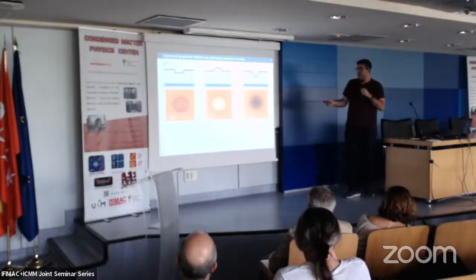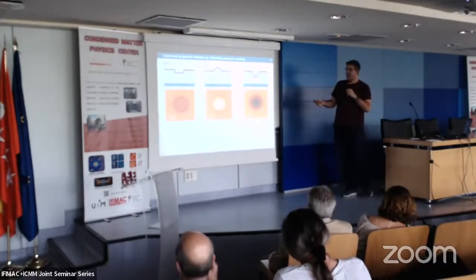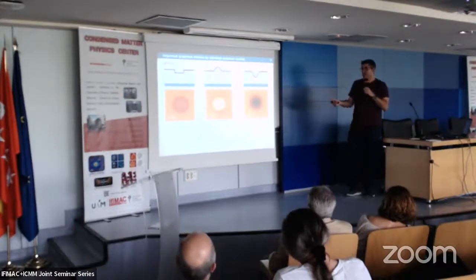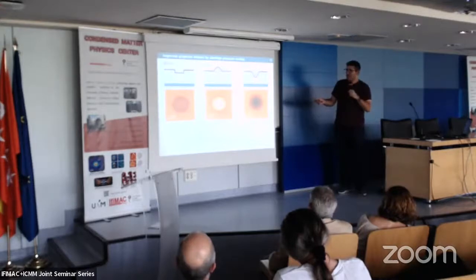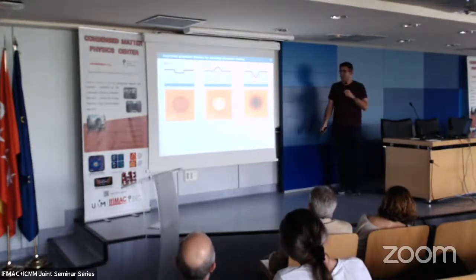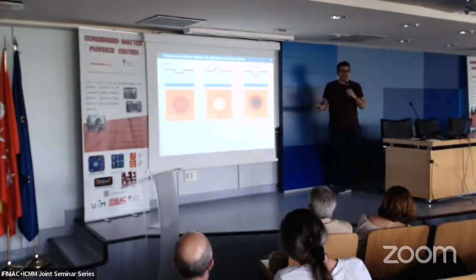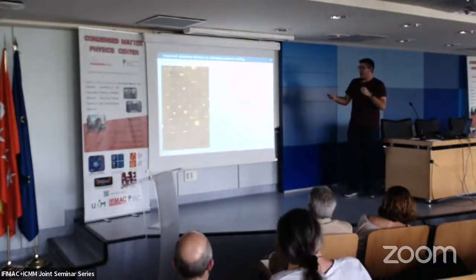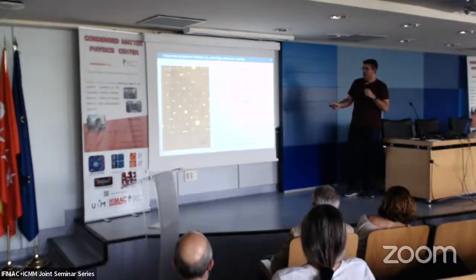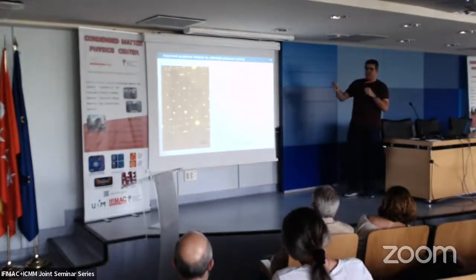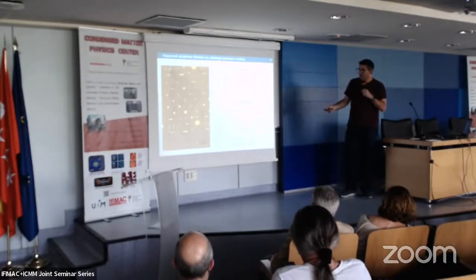Why is this happening indeed? The thing is the holes are not perfectly sealed. Okay, there is some leakage, and in principle there is some controversy in the literature about whether the leakage is occurring either through the graphene-substrate interface or by diffusion through the walls of the silicon dioxide. So we also wanted to understand what the main mechanism for the diffusion was. So we put graphene on top of many holes. We studied the inflation and deflation time constants of different holes with the distance to the edge, with the size and so on, and different configurations of pressures inside and outside the blisters. We also made a kind of simple toy model in which we consider all the leakage going through a cylindrical pipe, just connecting to the closest point of the edge. I mean, this is just to understand what was happening.